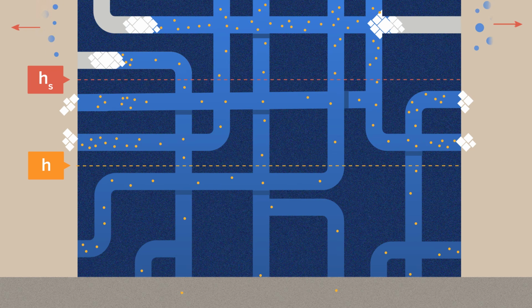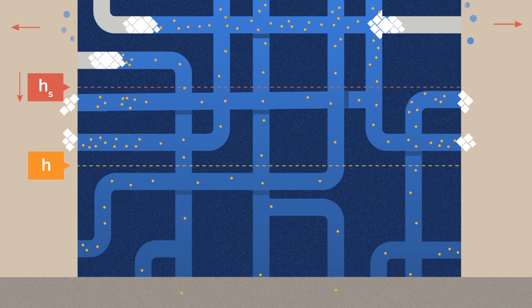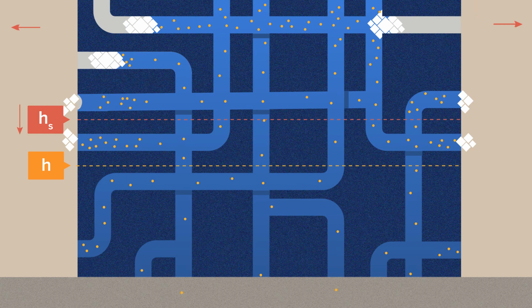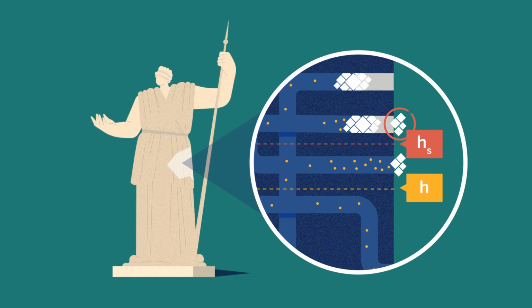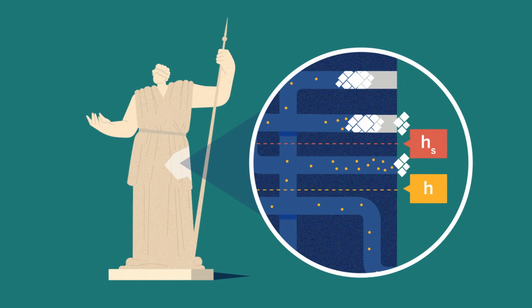Therefore, changes in relative humidity may displace the height boundary between efflorescence and subflorescence, just as changes in wind or temperature may do. This implies that zones where efflorescence is visible may become problematic at another point in time, or may, depending on circumstances, already have potentially damaging subflorescence forming.